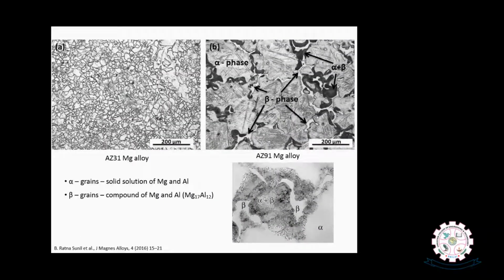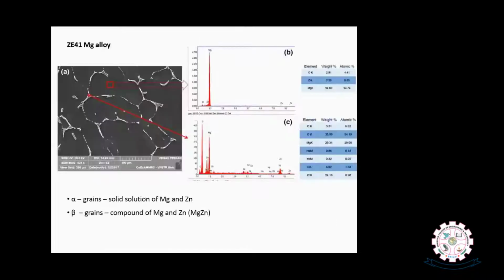And here you can see typical microstructures of AZ31 magnesium alloy and AZ91 magnesium alloy, where the aluminum percentage is increased from 3 to 9%. So if that is the case, you can see the presence of different intermetallics and formation of eutectic regions between alpha phase, those are the solid solution grains of magnesium and aluminum, and beta phase, where we see the development of intermetallic Mg17Al12. Between these two alpha and beta phases, the presence of black eutectic regions also, as shown in this diagram, you can see.